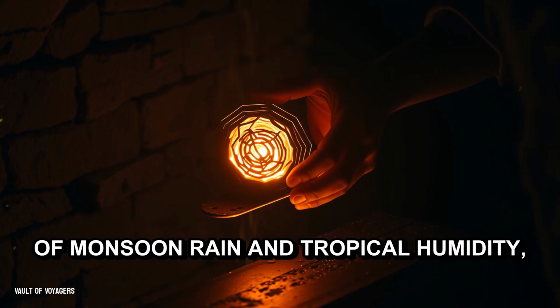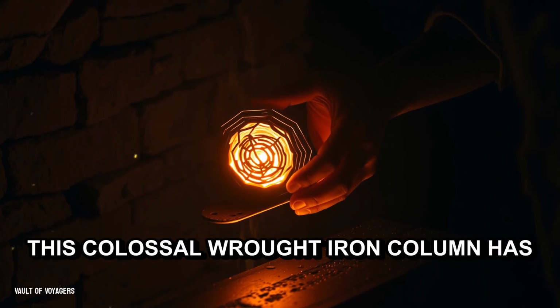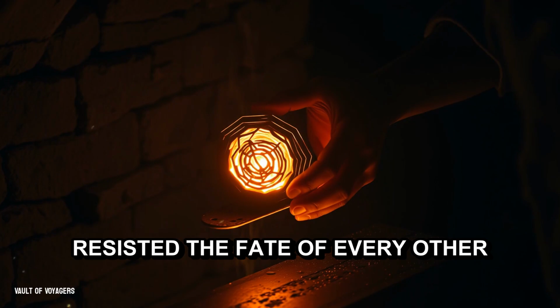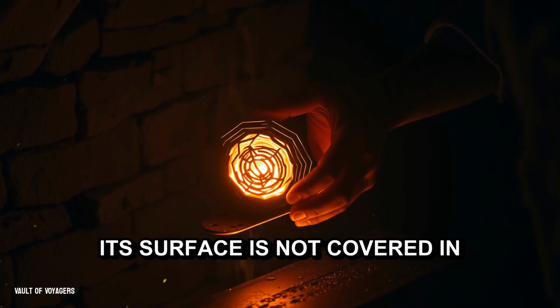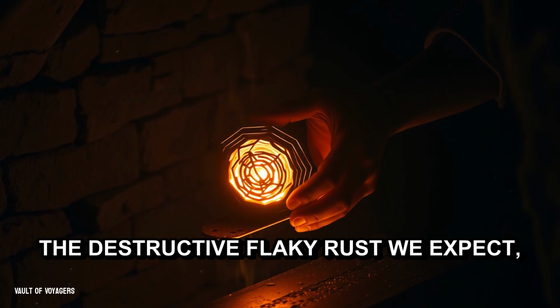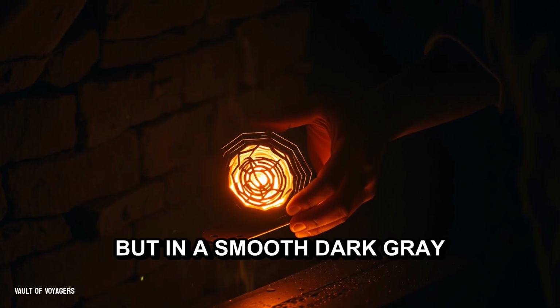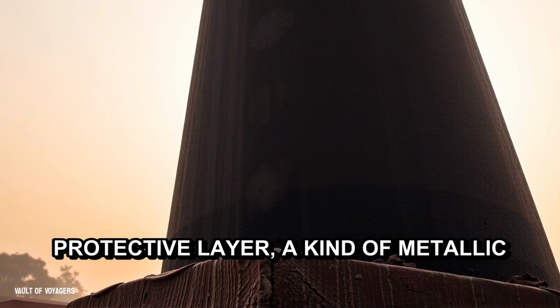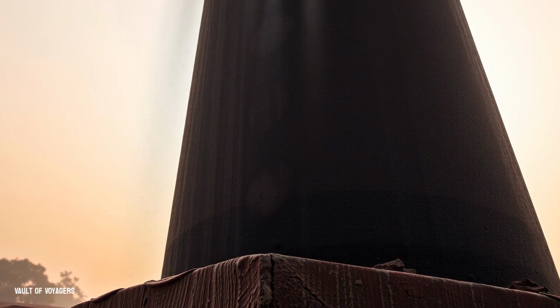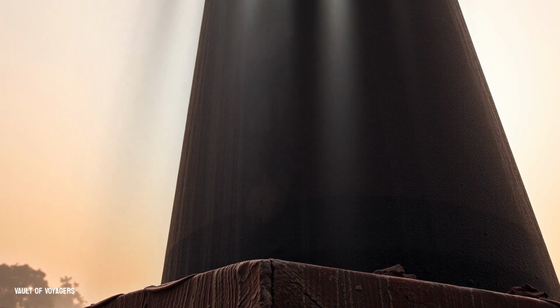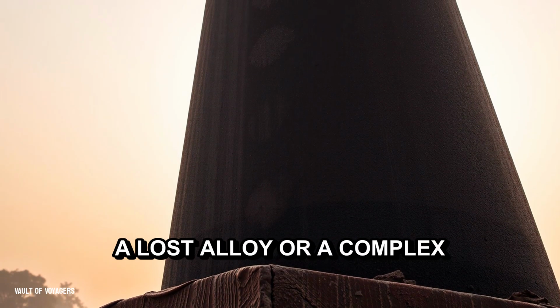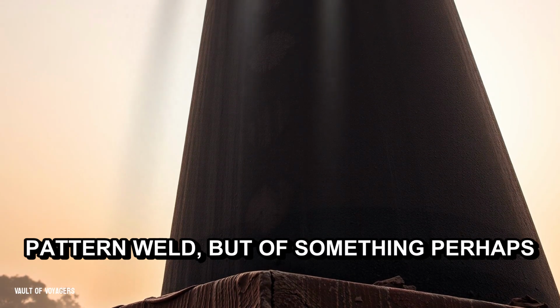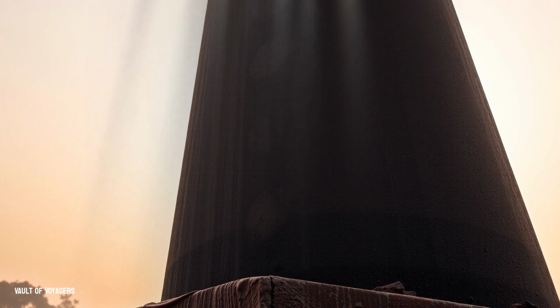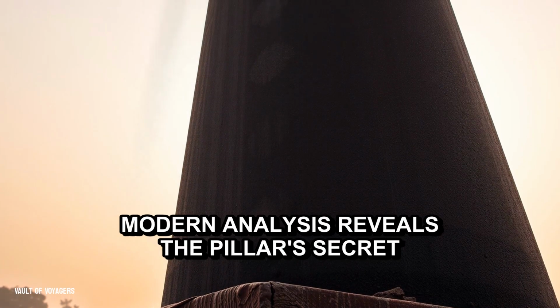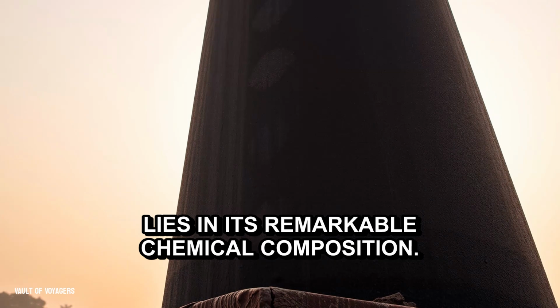For over 1,600 years, through relentless cycles of monsoon rain and tropical humidity, this colossal wrought iron column has resisted the fate of every other exposed iron object on Earth. Its surface is not covered in the destructive, flaky rust we expect, but in a smooth, dark gray protective layer, a kind of metallic skin that has successfully negotiated a truce with the elements. This is not a story of a lost alloy or a complex pattern weld, but of something perhaps more profound: purity and process. Modern analysis reveals the pillar's secret lies in its remarkable chemical composition.